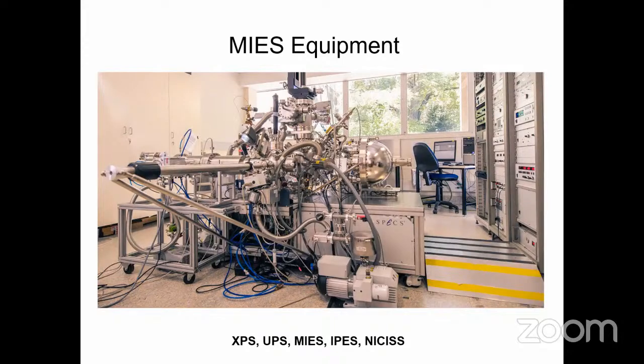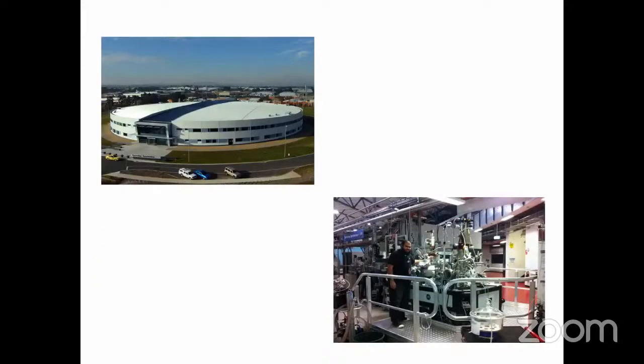Because we have a very small nanocluster, sometimes the intensity of this peak on the XPS is not that much. That's why we move to the synchrotron XPS. Synchrotron XPS is a huge radiation that we can narrow, actually the energy gap, and have a huge intensity to show us this amount, because we deposit a very little amount to avoid the aggregation of the nanocluster.